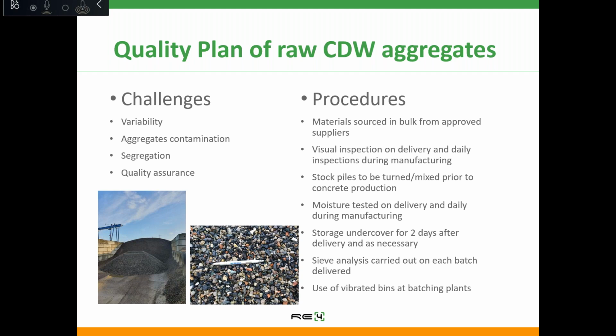Because we store the materials in stockpiles, these stockpiles need to be turned and mixed prior to concrete production to avoid segregation. We can store the aggregates under cover to avoid high levels of moisture. The moisture is tested daily during the manufacturing process. So if it's too high and you cannot use the aggregates, they are placed under cover so they can dry and be used in the concrete manufacturing.